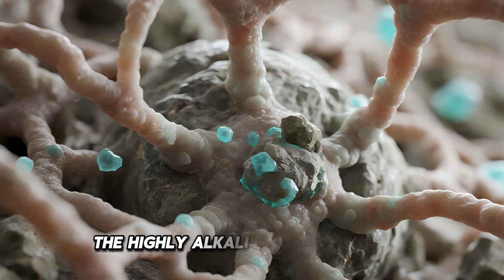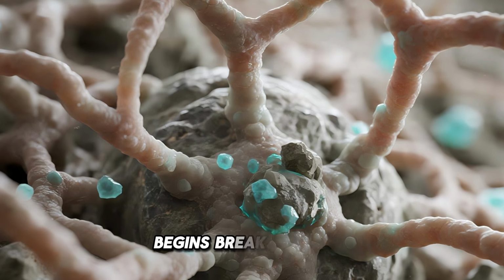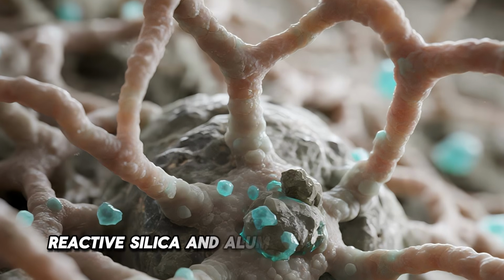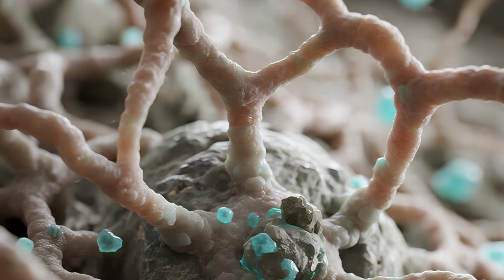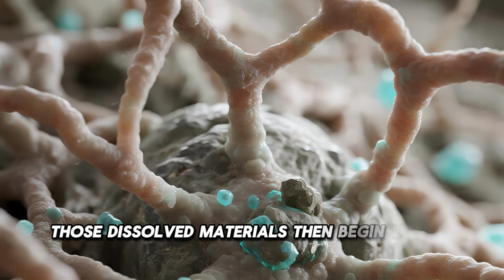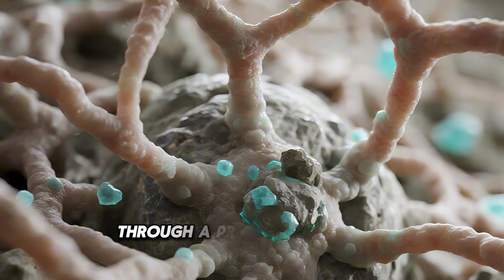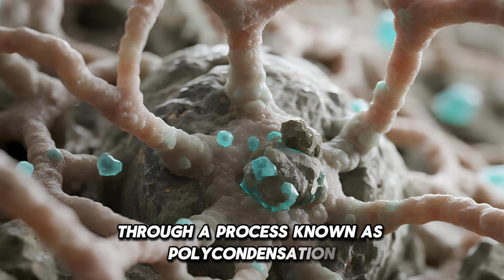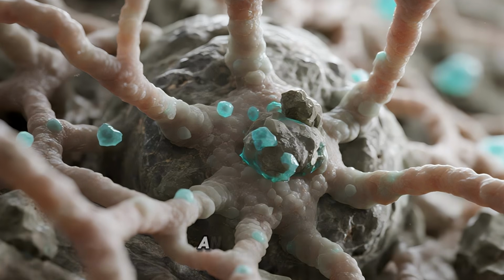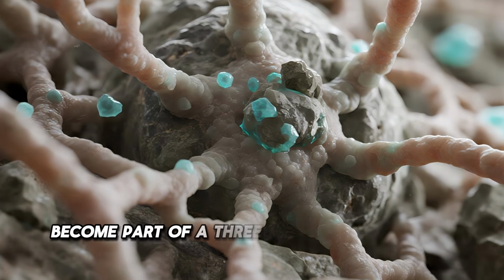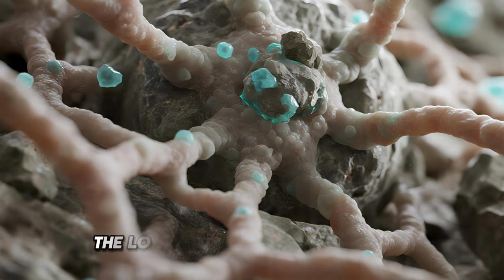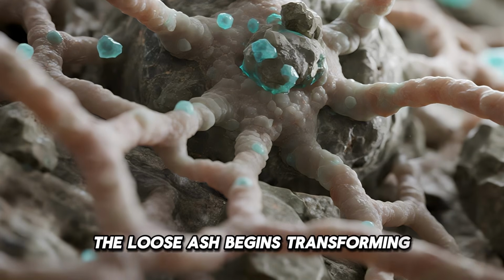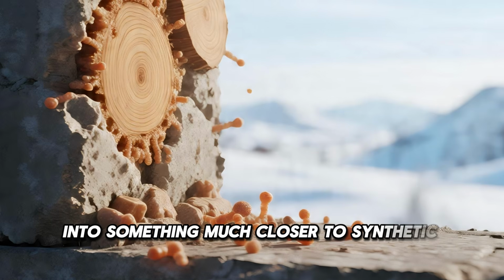The highly alkaline sodium silicate begins breaking down reactive silica and alumina phases in the ash. Those dissolved materials then begin linking together through a process known as polycondensation. Silicon, aluminum, and oxygen become part of a three-dimensional mineral network. The loose ash begins transforming into something much closer to synthetic stone.